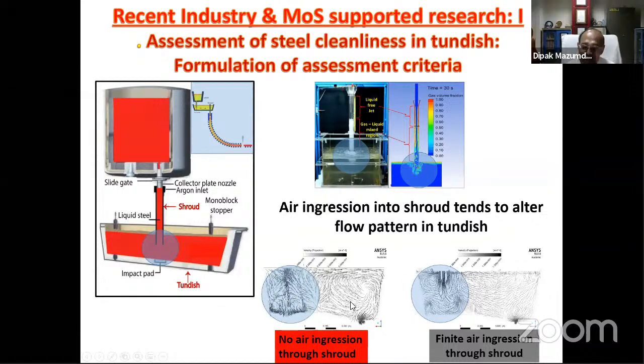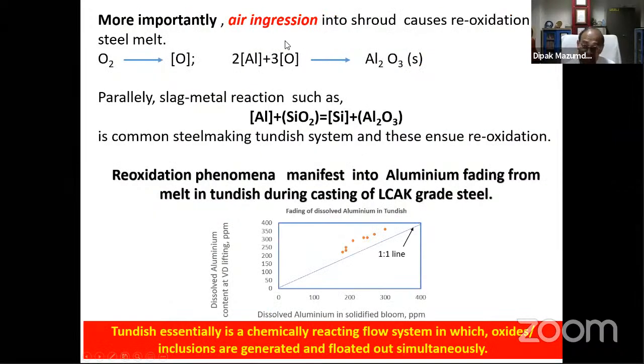It has only secondary influence, but nonetheless, the buoyancy exerted by the entrained bubbles could disturb the flow that is evident and which has been captured very realistically by carrying out numerical simulation. But that's not the entire story. Air ingression, when it takes place, then what happens, the oxygen from the atmosphere gets dissolved in the melt.